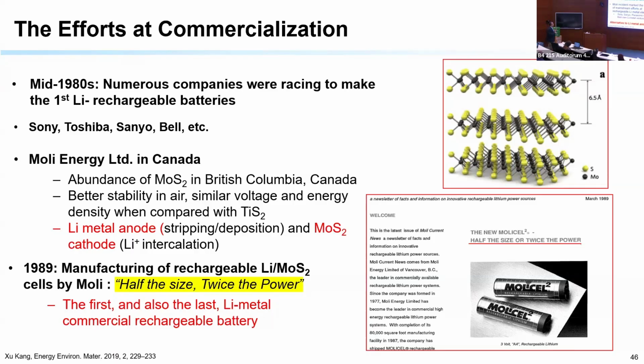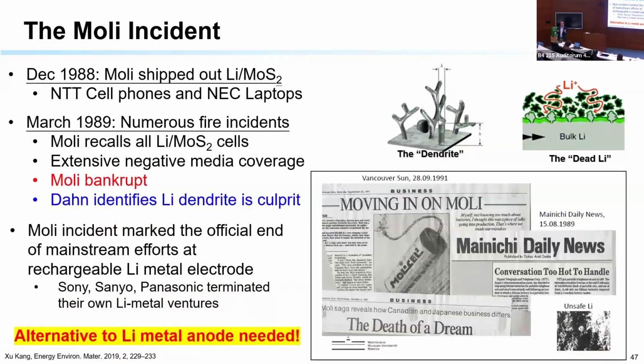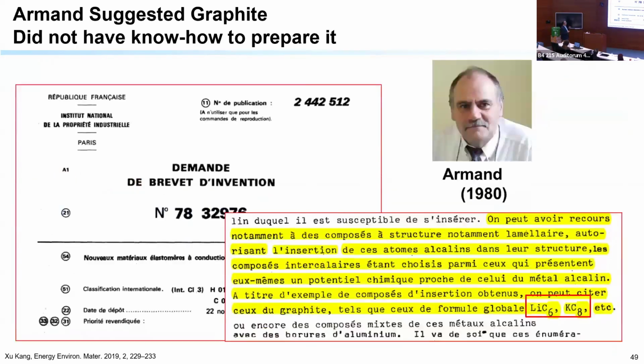But they were not so lucky. What happened is that lithium metal is very reactive, okay? And after a while, they sold a bunch of those, and the fires started, things started to explode. So very quickly, they went out of business, and they went bankrupt. Basically, they rushed, did not focus on safety, and this led to the destruction of the company. So people said, okay, we cannot use lithium metal, it's too reactive, we need another anode. So lithium metal was shelved, and people started to look for an alternative.